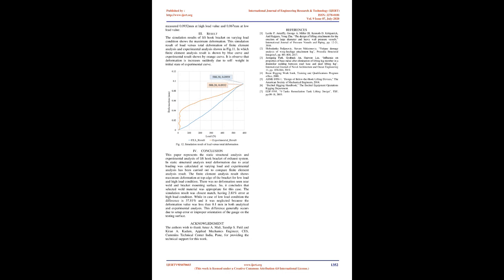For conclusion, this paper represents the static structural analysis and experimental analysis of lift hook bracket of exhaust system. In static structural analysis, total deformation due to axial loading was calculated at varying load, and experimental analysis has been carried out to compare finite element analysis result. The finite element analysis result shows maximum deformation at top edge of the bracket for low load and high load condition. There was no deformation seen near weld and bracket mounting surface. So, it concludes that selected weld material was appropriate for this case.